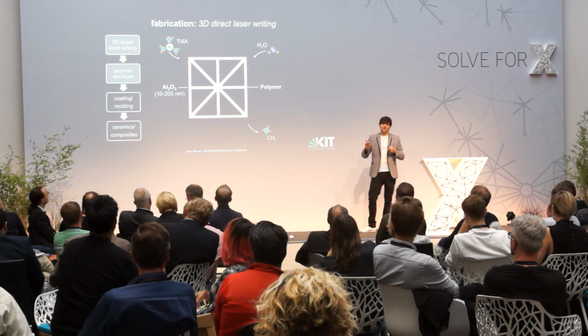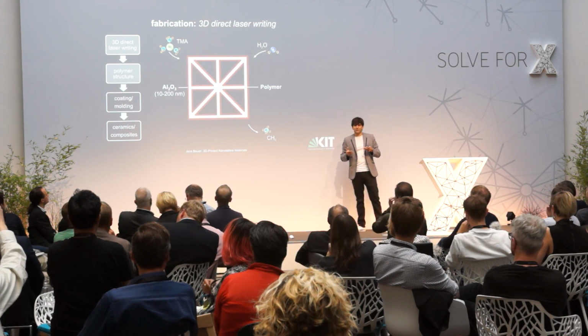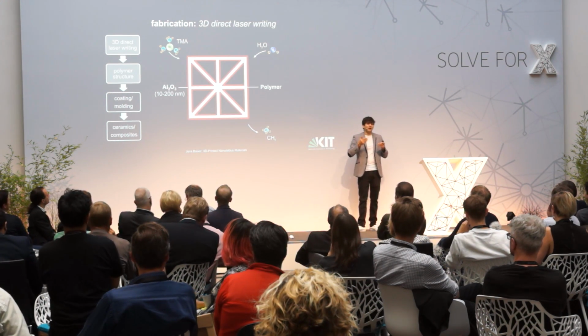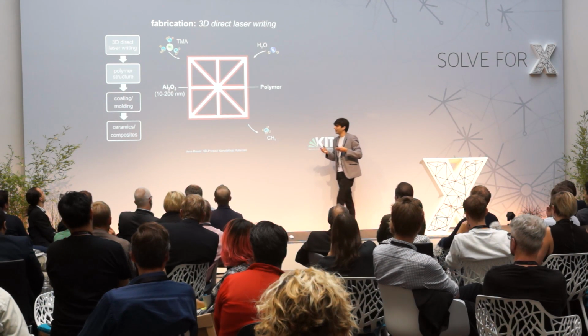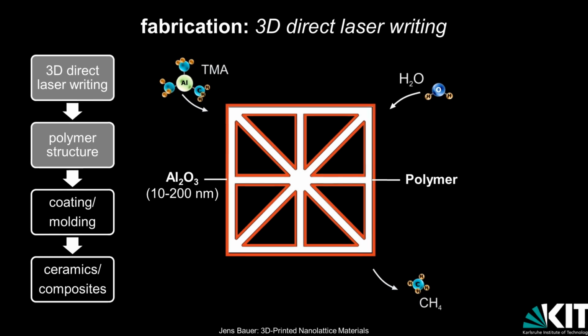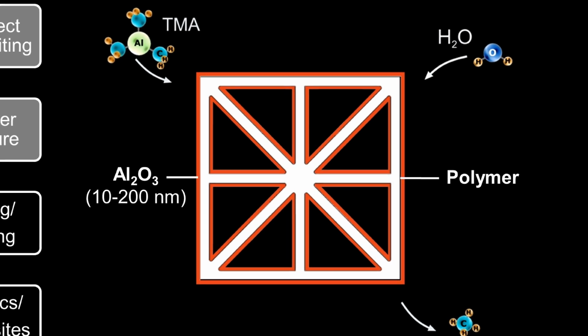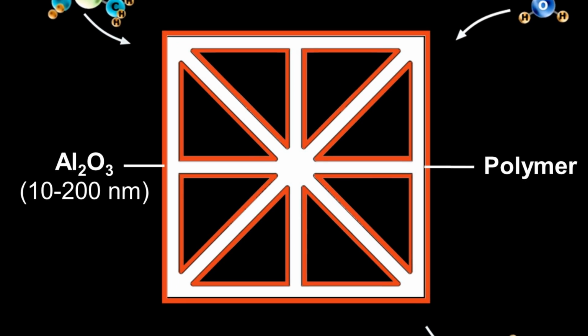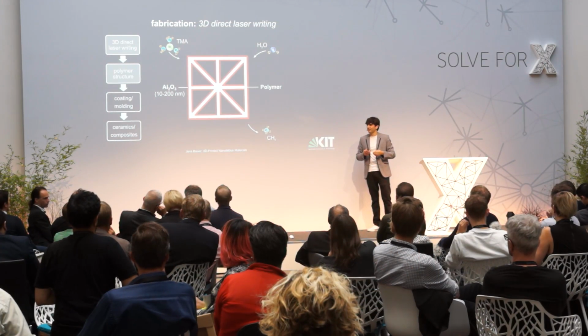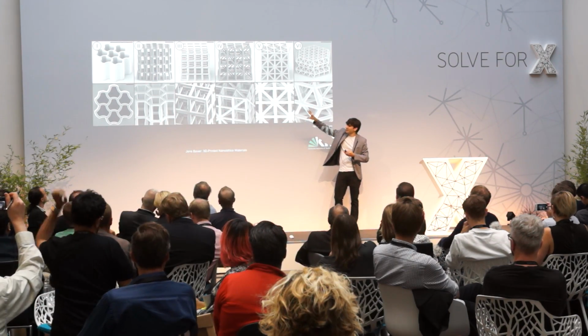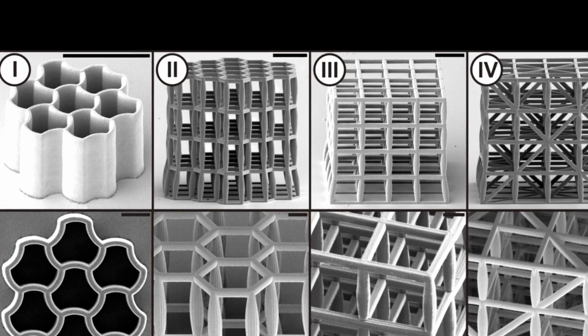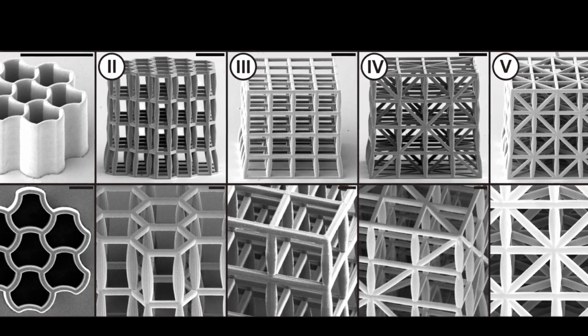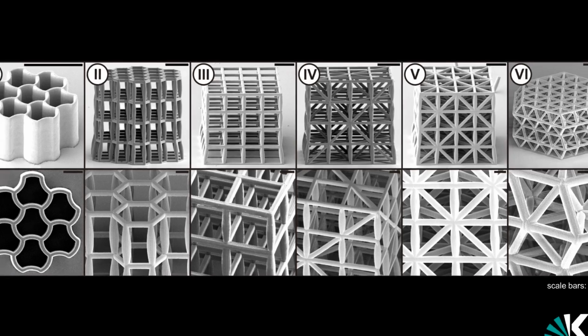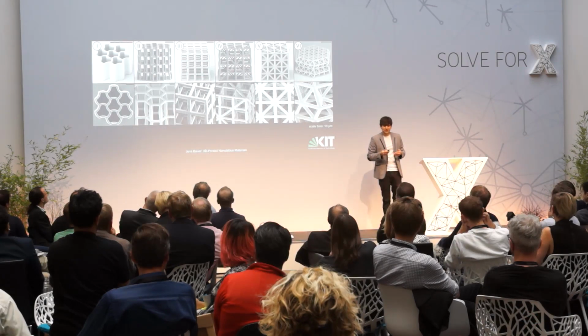Now, to take advantage of that mechanical size effect, which I mentioned, we need to apply techniques such as atomic layer deposition, which is illustrated here, to create ceramic or composite structures, because out of the printing process, we have a polymeric structure only. So with that method, we created different types of architecture. Here in the top row, you can see the entire structures, and in the lower row, it's a close-up view of the single unit cells, respectively. And all those designs have been optimized under different boundary conditions.